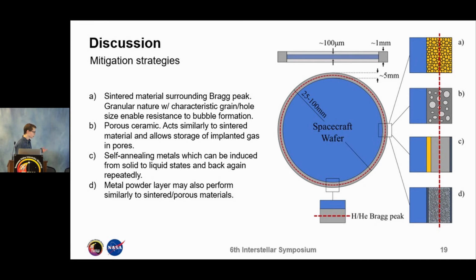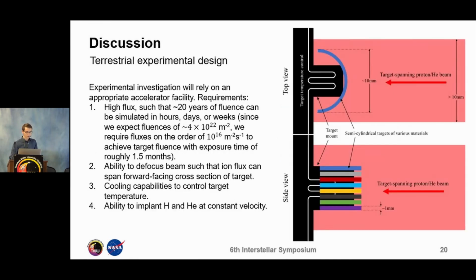In terms of discussing specific materials, a layered scheme with an initial layer of either sintered, porous, or powdered carbon, followed by a layer of tungsten is promising for 2 reasons. One, because carbon has a high energy onset of neutron production upon impact of protons, and tungsten is an efficient Bremsstrahlung X-ray absorber. So we would like to test these things empirically as well, ideally in a beamline, and it will rely on an appropriate accelerator facility. The accelerator facility will have to have high flux such that 20 years of fluence can be simulated in hours, days, weeks, or months.